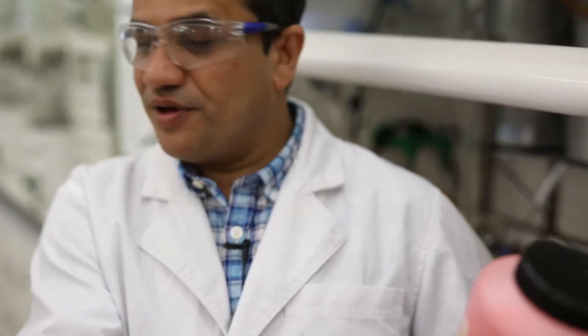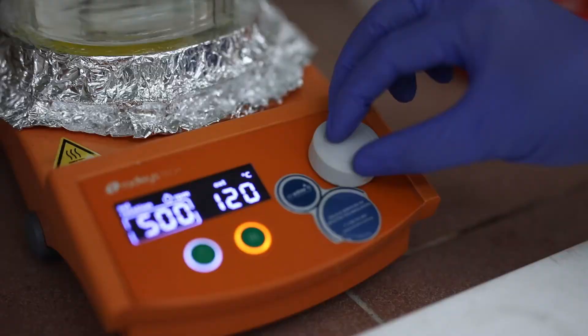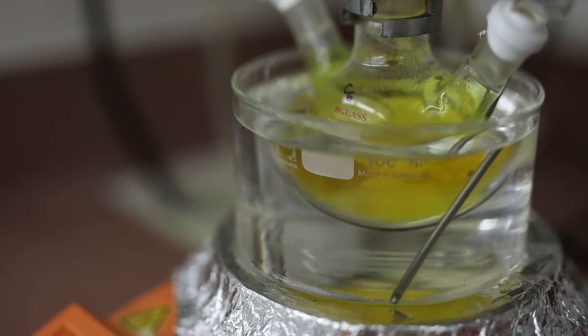So this new material which we have developed not only makes the charge transport process very easy, we have scientifically proved that by taking the contact angle measurement in the lab, where we put a thin film of our material and put up the water droplet, and it repels the water. That enhances overall stability.